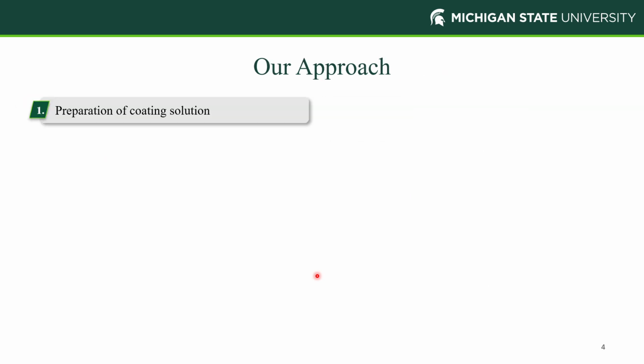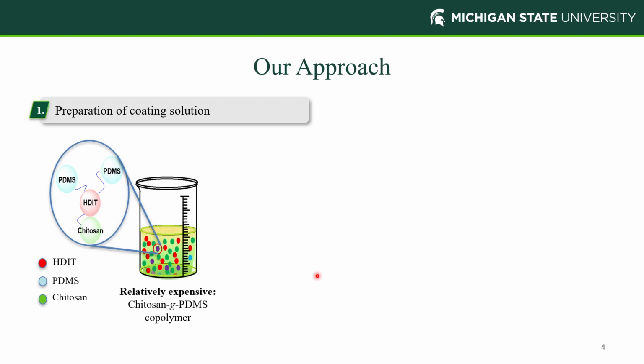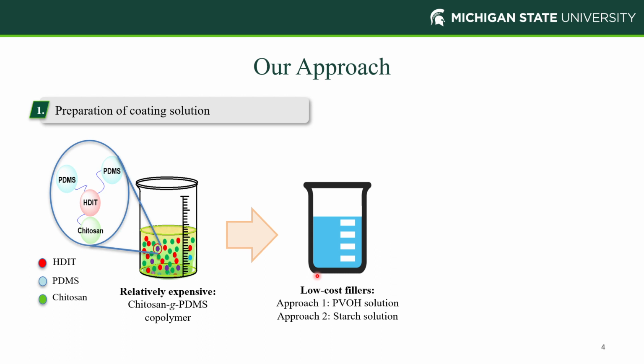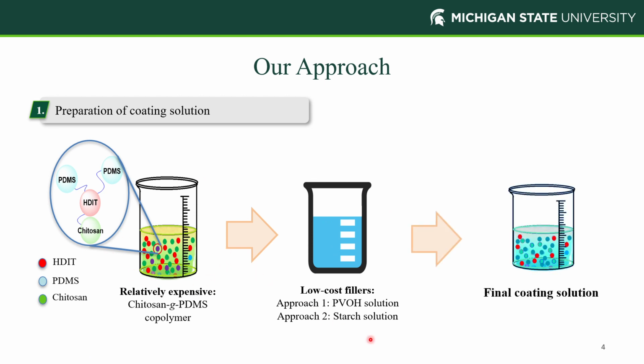So in order to replace this, our approach was simple. It was using the chitosan grafted PDMS copolymer, which is relatively expensive, and hence to reduce the cost, we are using materials that cost less, which are inexpensive, such as PVOH and starch. And our coating consists of 80 to 90% of these low cost materials and the chitosan grafted PDMS copolymer, and that gives us the final solution.